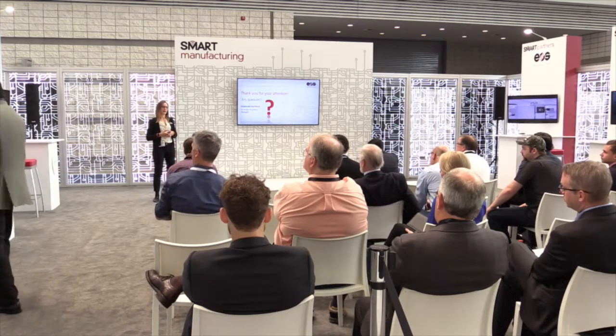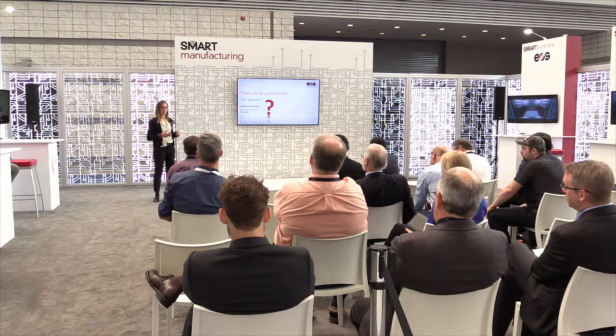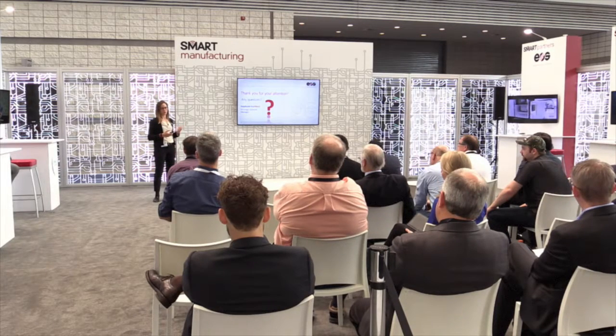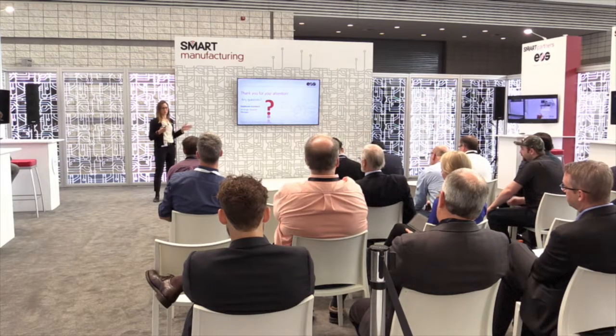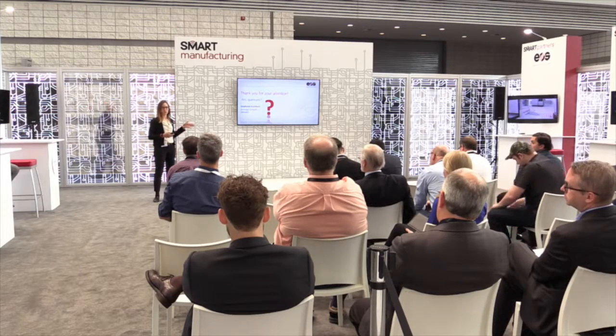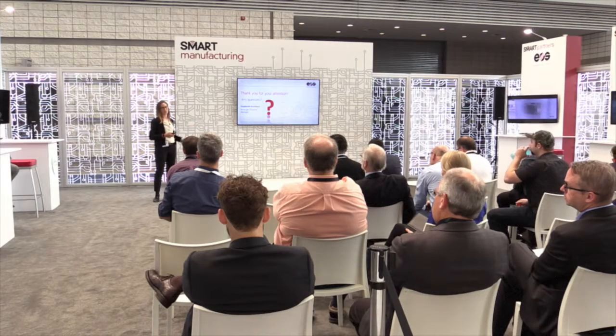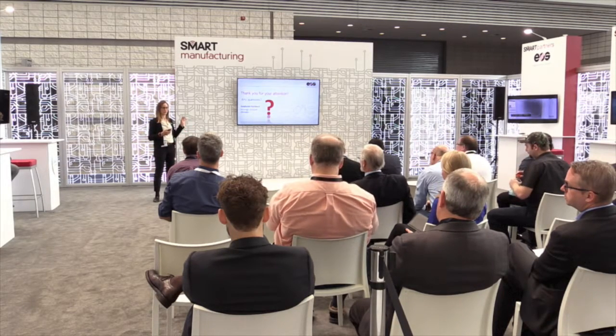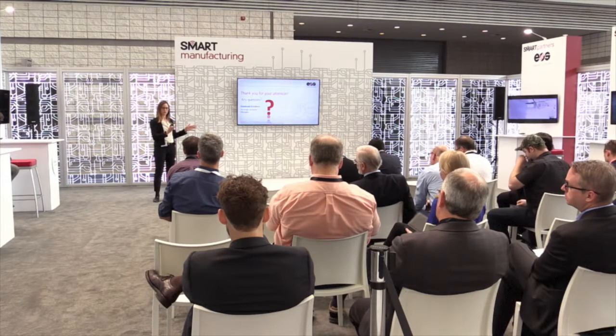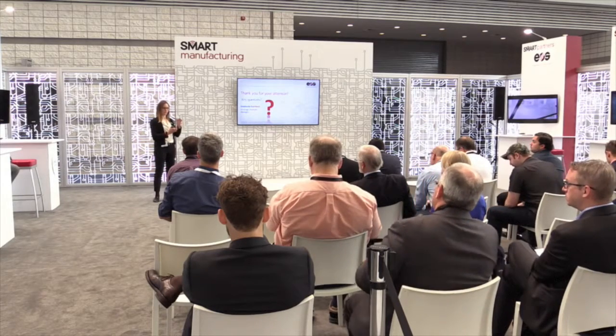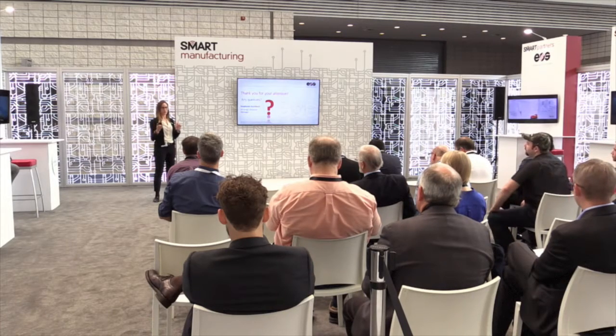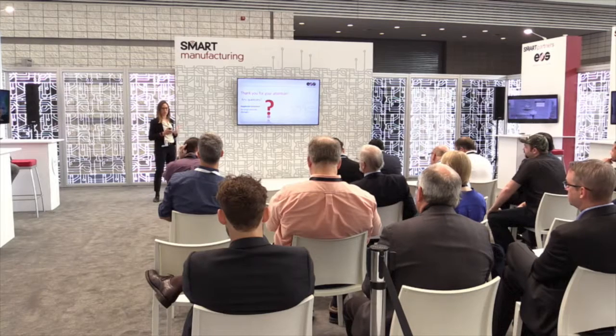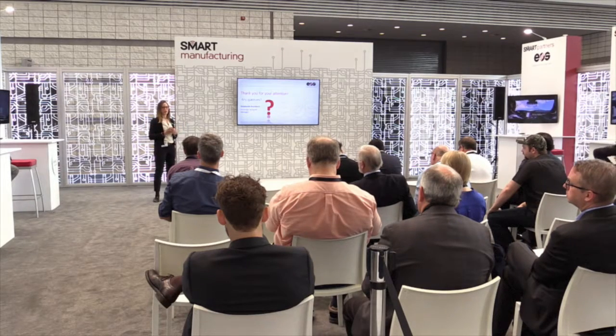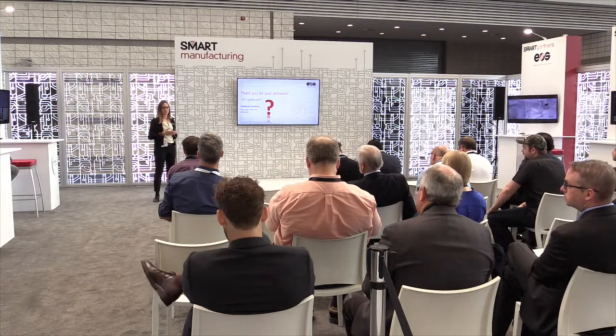And in terms of how that has an influence on mechanical properties when you refresh or recycle the material, that's part of the study we did. We not just looked at processability, if it's in general possible to reuse the remix powder, but we also pulled tensile samples after every aging cycle. And that showed that the mechanical properties, as well as the viscosity, more or less change after the first cycle. So if you start with 100% virgin new powder and you do the measurements, you have a certain value, and then you refresh it and do your next cycle, then your viscosity increases a little bit and your mechanical properties decrease a tiny little bit. It was less than about 1% maybe. So it was in a range that was really insignificant. And after that, doing additional aging cycles, it did not get worse.